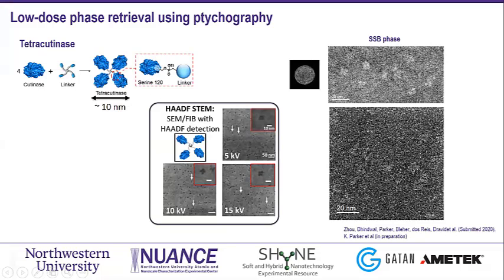On the right side here, I show, like I mentioned, a very fresh example from ptychography reconstruction using diffraction patterns like the one shown here, where you can really see the same structure, right? At least the morphology of that, the characteristic four lobes of the structure on a sample that was not stained. So meaning that was basically a pure sample at room temperature. So this is really exciting, and it shows a great potential using 4D STEM and then ptychography in this case for biological materials here.